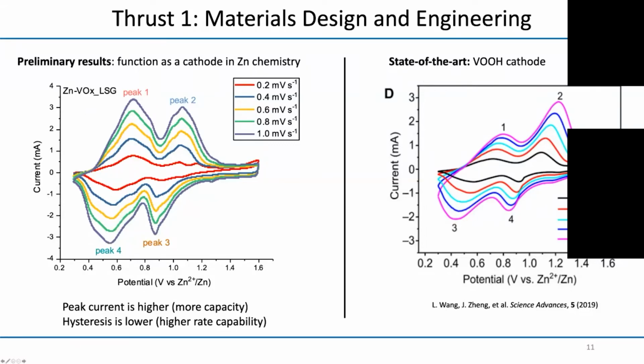Our preliminary results here show cyclic voltammetry curves between our material and a state-of-the-art material that uses vanadium oxyhydroxide. And the key takeaways from the cyclic voltammetry plot are two takeaways. The first is that the peak current is higher than that of the state-of-the-art, and these mass loadings are approximately the same. So this indicates that we might be able to store more capacity per unit weight using our material. And the second takeaway is that the hysteresis is much lower, the separation between these various peaks, which suggests that we might have less internal resistance due to the graphene scaffold, potentially enabling higher rate capabilities.